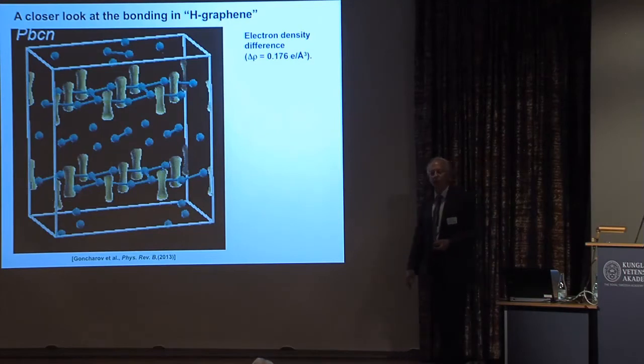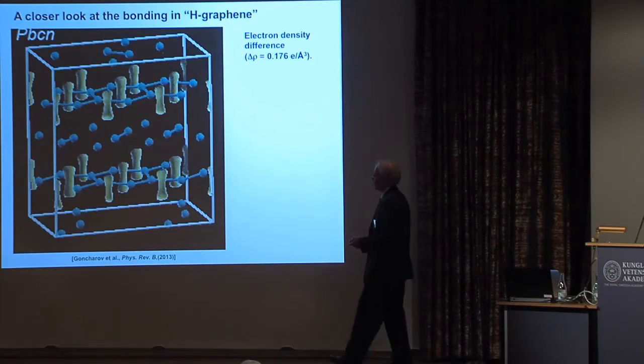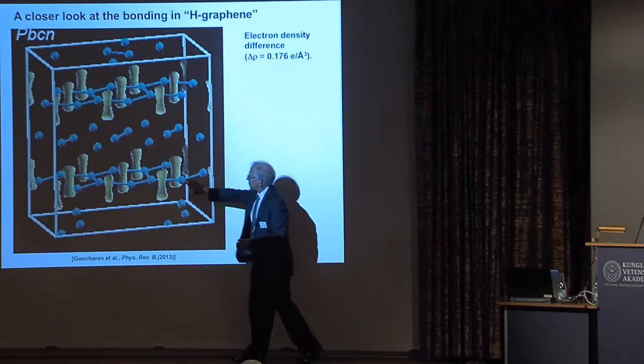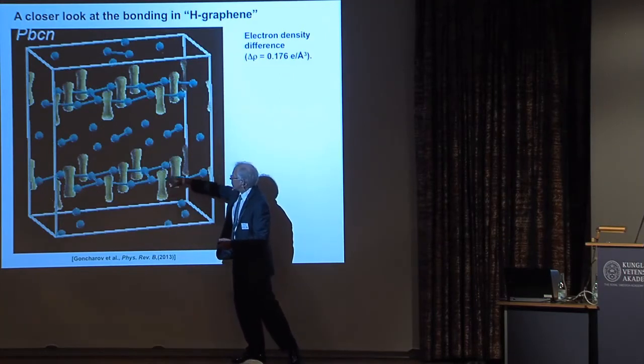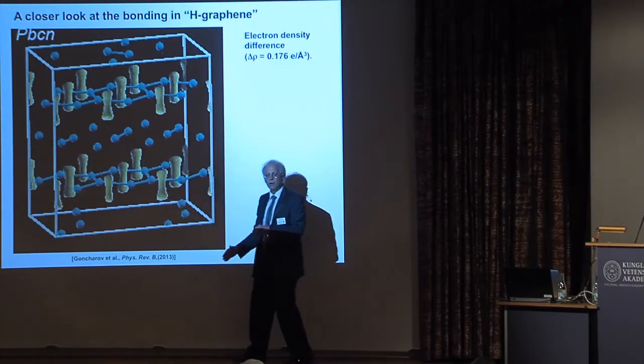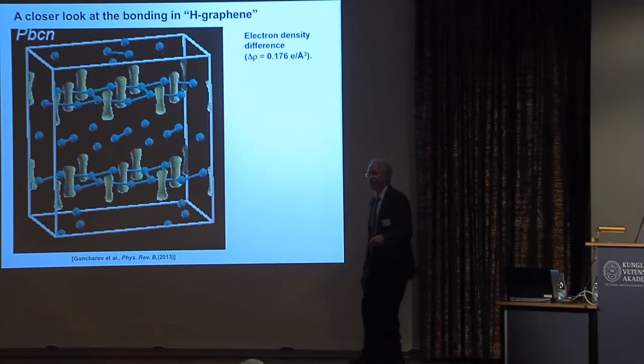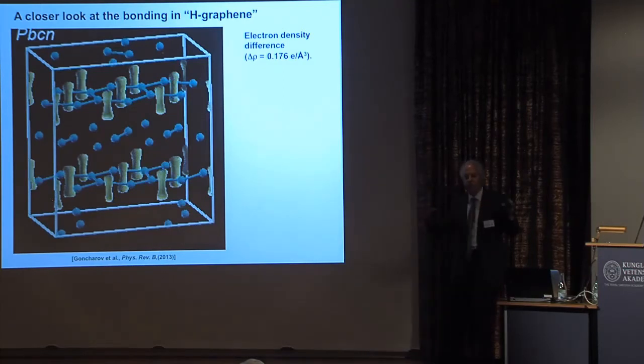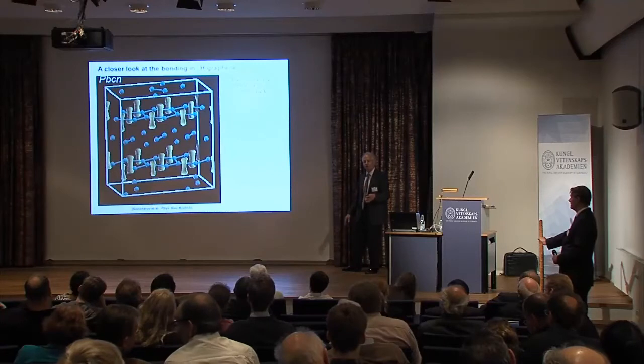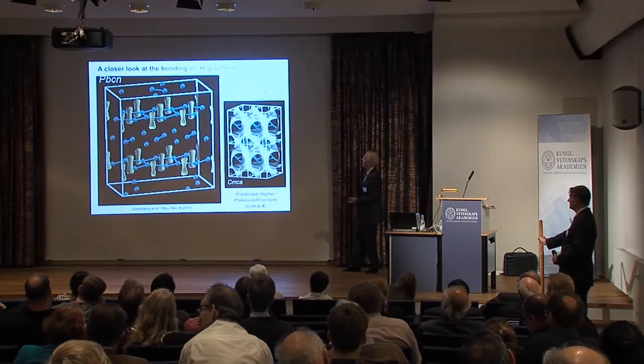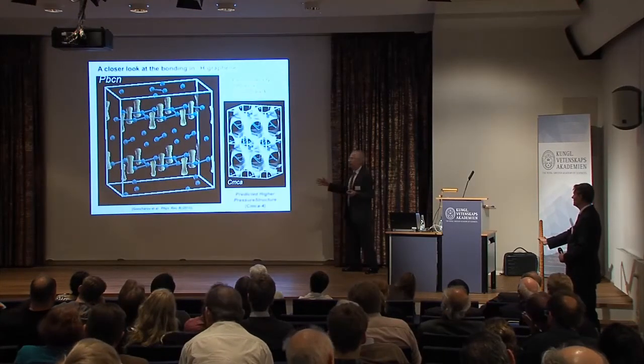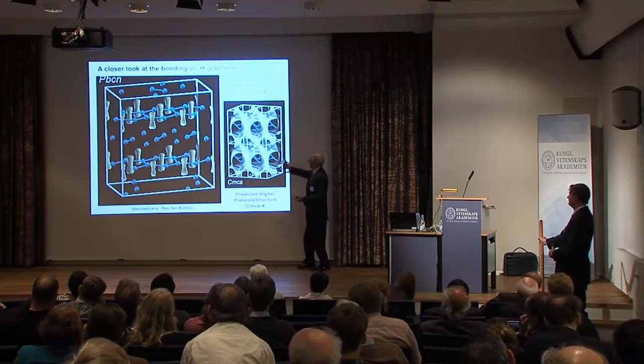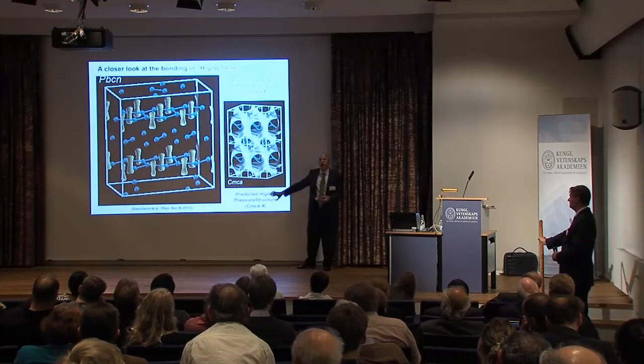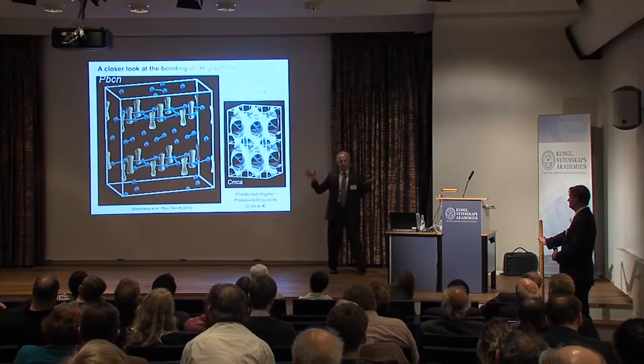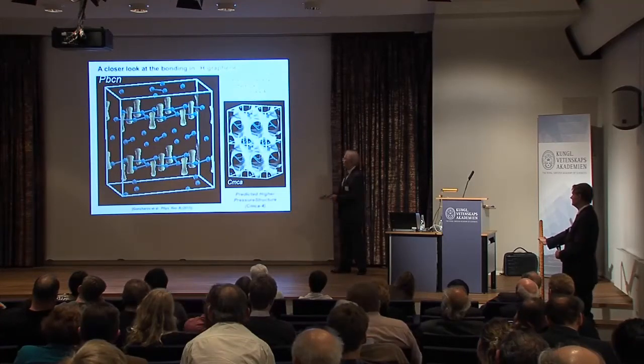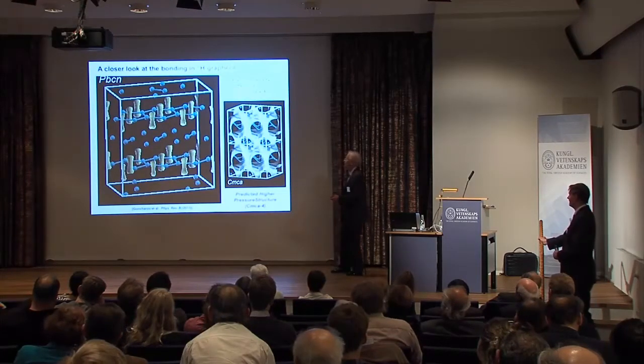Here is an image showing calculations of the electronic structure, showing the evolution of the bonding above and below the layer. So it's very much like carbon graphene. In fact, the electronic structure maps onto the electronic structure of carbon graphene beautifully. At higher pressure, still different structures, evidence for this interstitial electron density, like we have in the other alkali metals. These structures have not yet been seen.